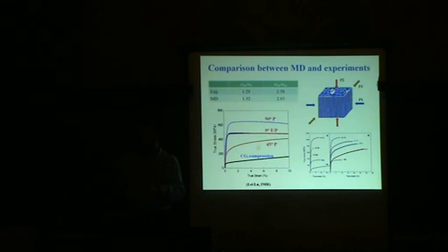Okay. And in essence, you can create a lot of geometrically necessary dislocations. That creates a huge work hardening. Right? Because you only allow one kind of dislocation to shoot in one direction. Those are geometrically necessary dislocations. They create a huge work hardening in the system, make the material very stable, much more stable against instabilities.